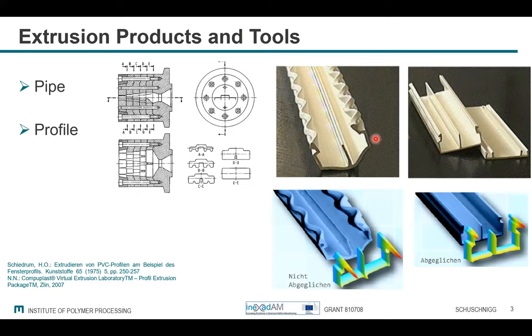After a proper simulation and a proper setup of the die, they got this profile out. You still have a little bit of a shooting out of the velocities at these tips, but it's okay. And the profile came out straight with straight edges. And so therefore, this was not really a problem.